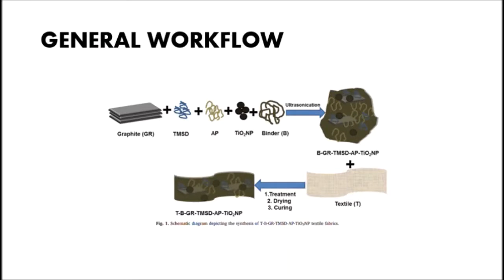So we can see here the synthesis of the coating. The smart coating was developed as represented here. The GR, AP, TMSD, and TiO2 NP were dispersed well in the solution using the ultrasonication process. And then the furniture fabric was coated with the dispersion. After that, the fabric was treated, dried, and cured.